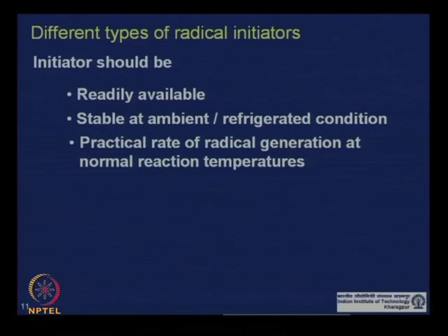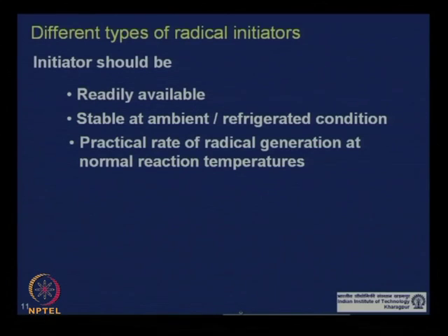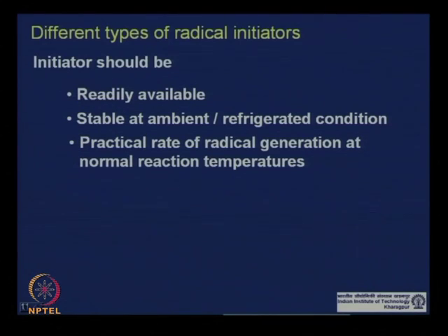So, these are the three criteria an initiator should fulfill. One is that it should be readily available, of course, especially for commercial application. Second, it should be stable at ambient condition. If you are storing it at room temperature, or even in a refrigerator, it should be stable in that condition. It should not generate radicals under the condition of storage. And the third one we just talked about: it should generate radicals at a practical rate at normal reaction temperature. It should not be too slow, making the reaction take much longer, or too fast, as there are possibilities of hazard because of the exothermic reaction happening at a much faster rate.